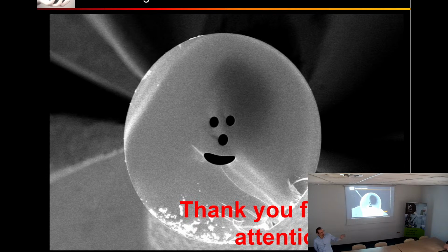Of course, if the temperature is too high and if the duration is too long, you have crystallization in all your glass. So by choosing the right temperature and right duration, you can obtain a profile.